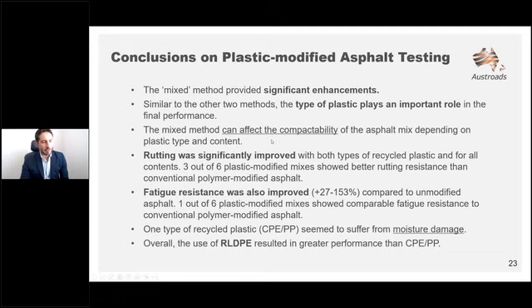Be aware that there can be an effect on the densification behavior, so on how easy it is to compact, depending on how much plastic you use and the type of plastics you're using. Rutting was definitely improved, and in 3 out of 6 cases, the plastic modified mixes were actually better in rutting compared to the A35P, the conventional polymer modified asphalt. Fatigue resistance was also improved, as I said, by between 27 and 153% extra fatigue life compared to unmodified asphalt. And in 1 case out of 6 mixes, there was comparable fatigue resistance with conventional polymer modified asphalt.